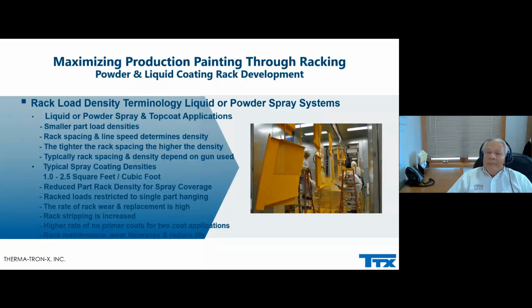In powder, you can get multiple colors and multiple thicknesses. In the case of color coding for electrocoating, if you have 50%, that's where your justification comes in. If you're doing multiple colors, say 40% of one color and 40% of another and the rest is 20%, you can probably design the line with skipping those electrocoat areas and applying just a powder top coat, single coat. So there's numerous ways of approaching it.